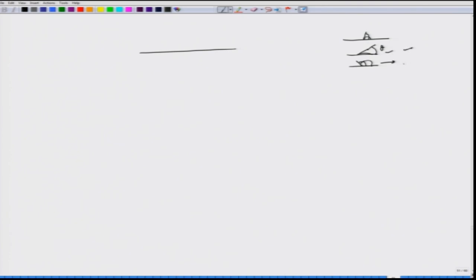So this is hydrophilic, this is hydrophobic, this is in between, and then we have the super hydrophobic surface, where the contact angle is generally more than 140 or 145 degrees. One of the super hydrophobic surfaces is the lotus leaf. If we put a water droplet there, it dances on that surface, and it helps in cleaning the lotus leaf, because when we tilt it, the water falls down, takes the dirt particles along with it, and the leaf gets rinsed.